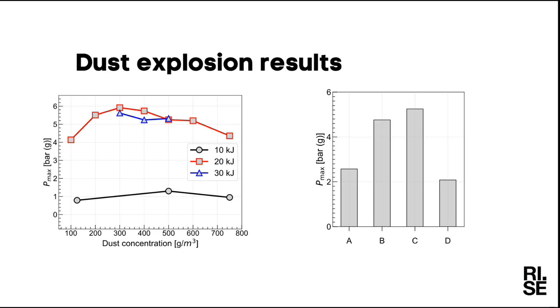And then finally, we did some explosion tests in our small-scale 20 liter vessel. Here on this figure, you see the dust concentration on the x-axis, and the y-axis is the maximum explosion pressure. As you see, using a 10 kilojoule igniter, which is the value recommended by the standard test, we didn't get high explosion pressure. However, when we increase the ignition energy to 20 kilojoule, for a certain concentration we get around 6 bar explosion overpressure, which is a considerable explosion risk. And if we increase the ignition energy further, the explosion overpressure is not further increased.